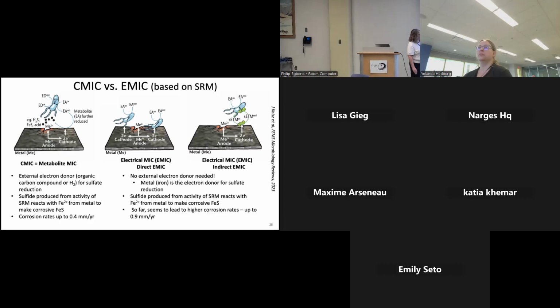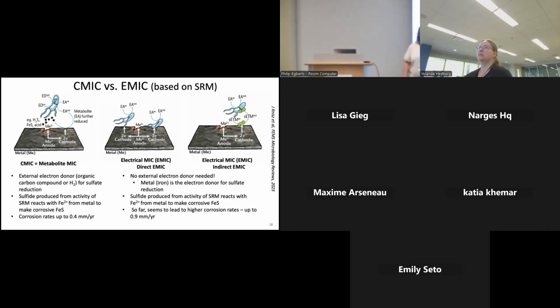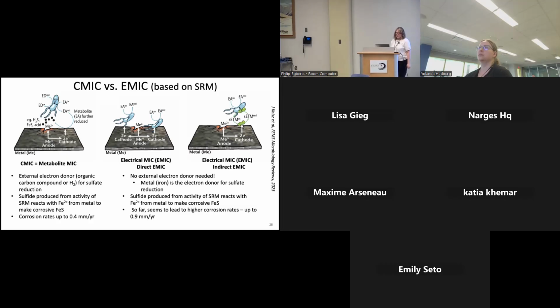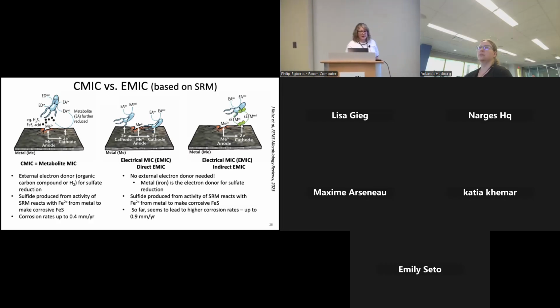In terms of electrical MIC, again, it can be direct somehow or indirect. The metal itself is the electron donor, supplying those electrons to sulfate reduction. And so far, a lot of the studies, at least in the laboratory, have shown that this type of mechanism was way more corrosive, up to about 0.9 millimeters per year. These are mechanisms that have been studied in the laboratory setting.